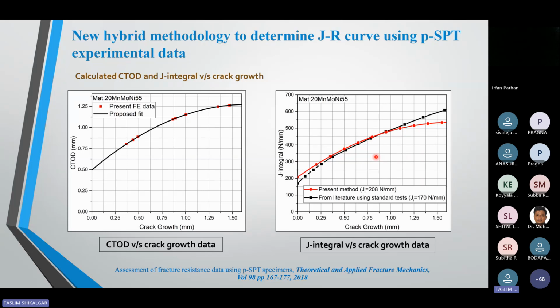Here is a comparison between the J integral versus crack growth data. Here I got a good correlation compared with the literature data from these PSPT specimens. So this is one of the important challenges I achieved with the help of these specimens. And I published this data in this paper, assessment of the fracture resistance data using the PSPT specimens.